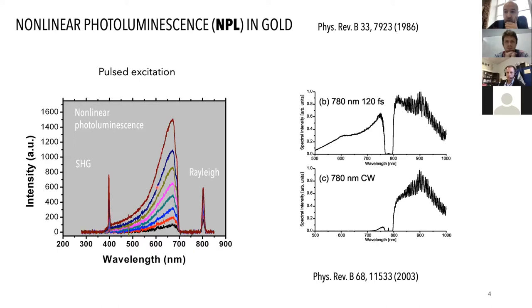It doesn't really matter. It's basically gold in some sort of nanostructured form. I'm not going to be talking too much about it, but the shape of the spectra does depend on what kind of structures you're looking at. This would eventually be modified by resonances. If you have, for instance, a surface plasmon resonance, the shape of the spectrum will be affected. But I purposely show this very plain spectrum where there's no surface plasmon resonance shaping the spectrum, just to extract a little more of the physics that I will be explaining later. Okay, but yes, go ahead.